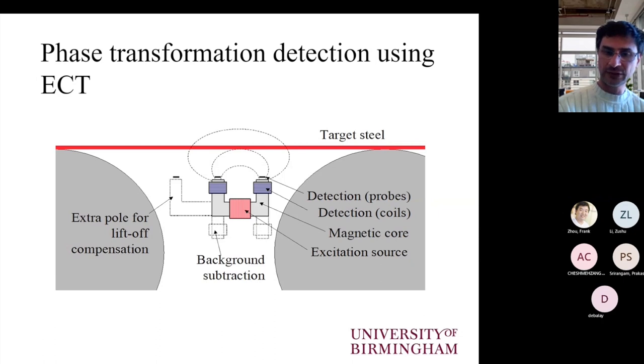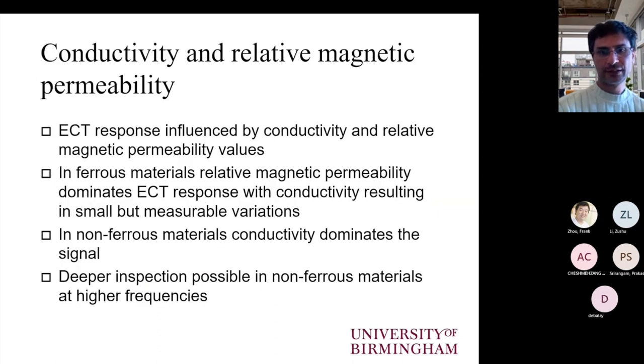However, we can still take conductivity-related readings that enable us, to a certain extent, to extrapolate at what temperature our strip is at a particular stage of cooling. It is very important to recognize the importance of conductivity, but we also have to take into account that the dominant effect relates to the relative magnetic permeability. So the more the relative magnetic permeability increases, the lower the significance of conductivity will be.